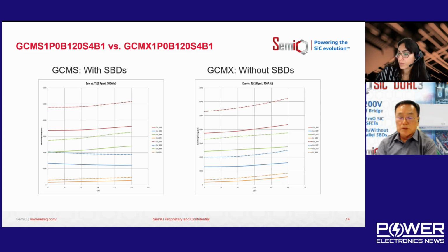So the reverse recovery charge is independent of temperature or slew rate. You can see on the left side is with the silicon carbide diode, and the right side is without silicon carbide diode. GCMS is with a diode, GCMX is without diode. You see the total switching energy is below 50,000 microjoules. So it's 50 millijoules. And then this is higher than 50 millijoules, even at room temperature.